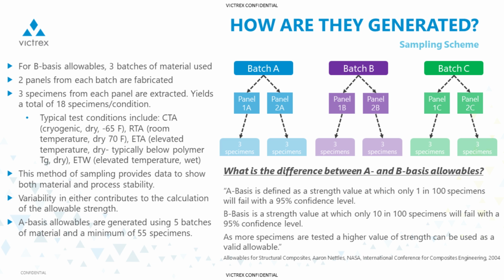The conditions generally range from CTA or cryogenic temperatures dry, which is generally -65 Fahrenheit, all the way up through elevated temperature dry and elevated temperature wet testing. And typically the elevated temperature used for testing is below the polymer glass transition temperature. This method of sampling provides data to show both material and process stability or variability. And that variability contributes towards the calculation of the allowable strength.